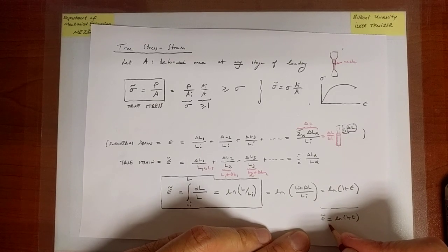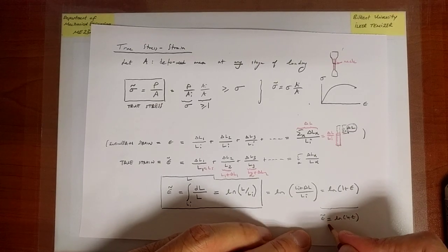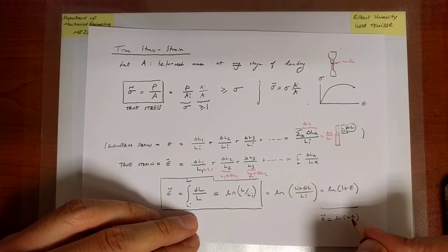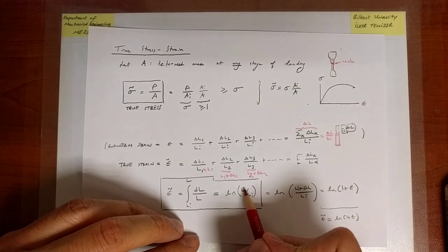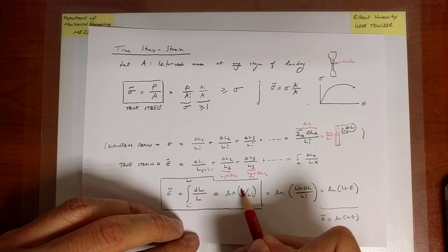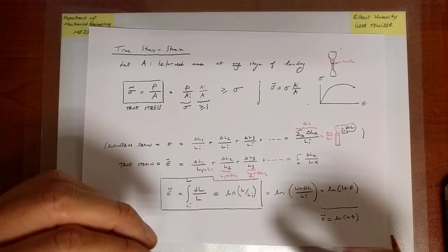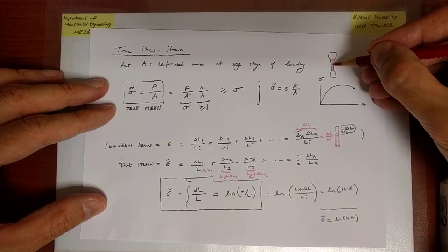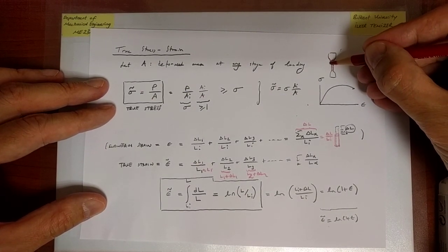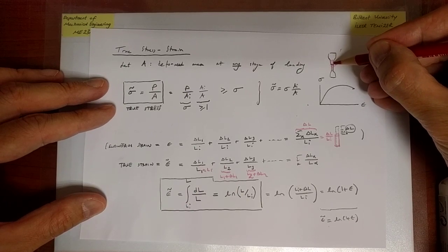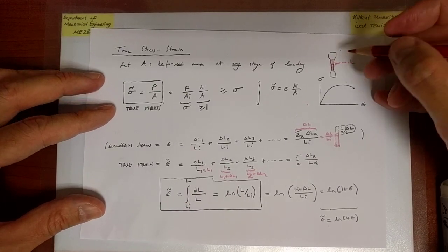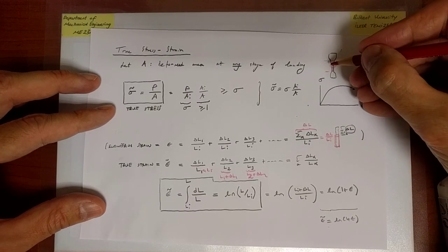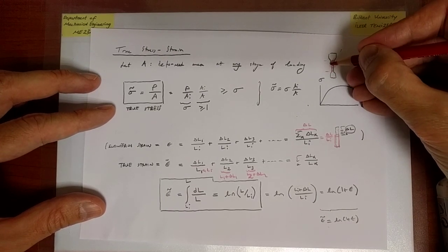The reason is that we are monitoring the strain, either true strain or the engineering strain, through quantities that have to do with the length of the gauge portion, but the length of the gauge portion after a while becomes meaningless because all the deformation eventually localizes into a very small region that we called necking, and if you monitor the strain over the whole gauge portion, you are essentially making a mistake.